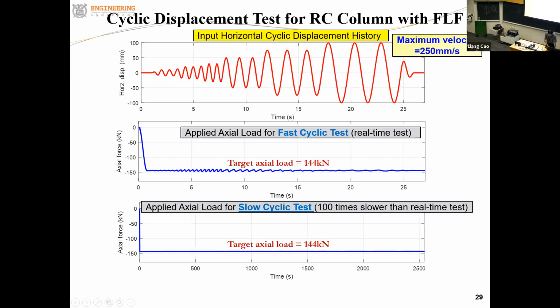And this figure shows the controlled axial force. We wanted to apply the constant axial force during the cyclic loading test. And that's the controlled or measured axial force for the fast cyclic loading test, where the maximum velocity is about 250 millimeter per sec. So it's almost constant, as you can see here. Target force is 144 kilonewton. Although we have some fluctuation here, it's small, less than 5% of the 144 target force.